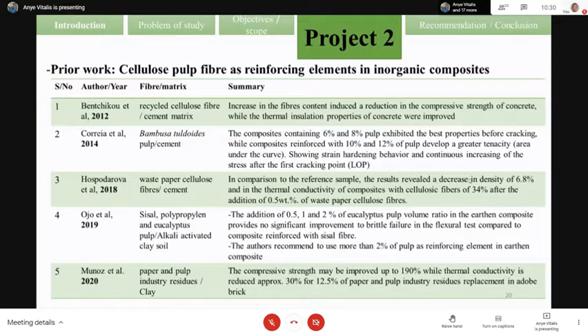There is also Correia et al. who studied Bambusa tuldoides pulp in cement mortar, and realized that by using 6 or 8% of this cellulose fiber in the cement mortar, there is an increase of the modulus of rupture. But by using 10 or 12%, there is a significant development of the tenacity, which shows strain hardening behavior and a continued increase of the stress at the first crack.